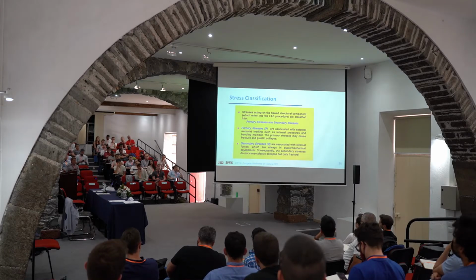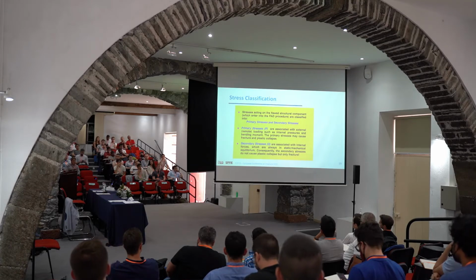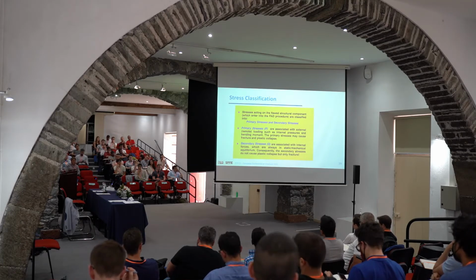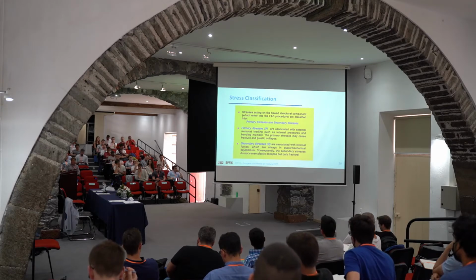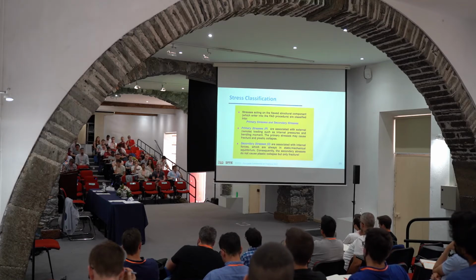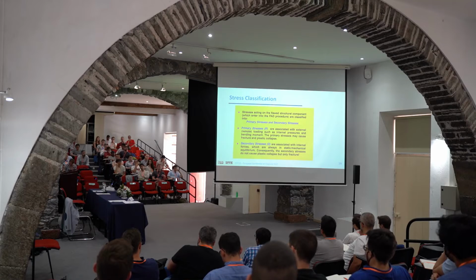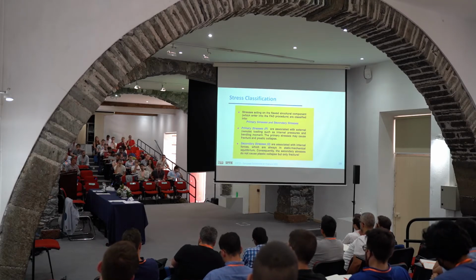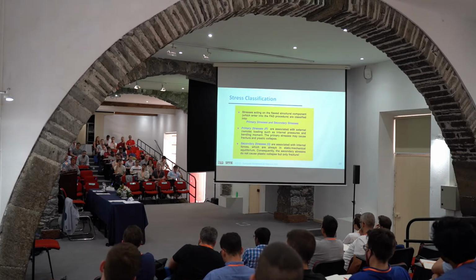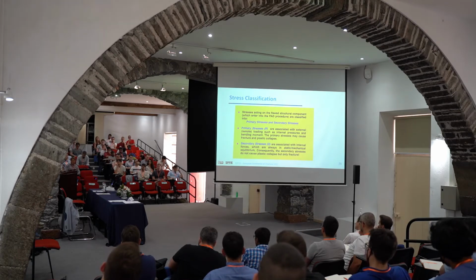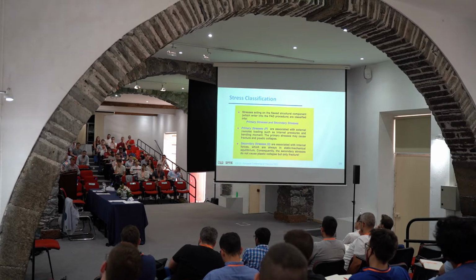Okay. And the other thing that you need to consider when dealing with this defect assessment methodology is the stress classification. And that's because this is a general view. Of course, there are a little bit more details, but let's say 90% comes to this. You have either primary stresses and secondary stresses. Primary stresses are loading. For example, this is an example of a pipe with a longitudinal crack. Okay? The primary stresses are the stresses coming from the internal pressure. That's the load. Okay? The secondary stresses are, in most cases, associated with residual stresses.